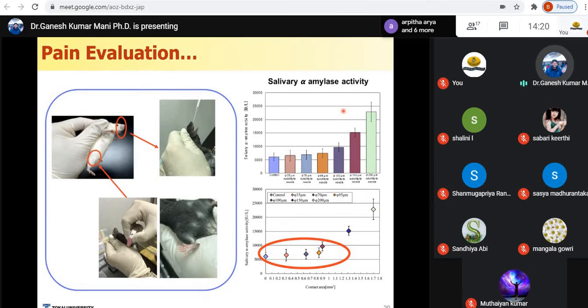Then we tried different sizes of microneedle, say 50 micrometer, 100 micrometer, 200 micrometer. What we finally found is that if your microneedle is less than 95 micrometer, the effect is almost the same as the mosquito's labium. But if the size exceeds 95 micrometer, it is almost the same as the usual commercial needle. So that's why we limited our research work to 95 micrometer only.